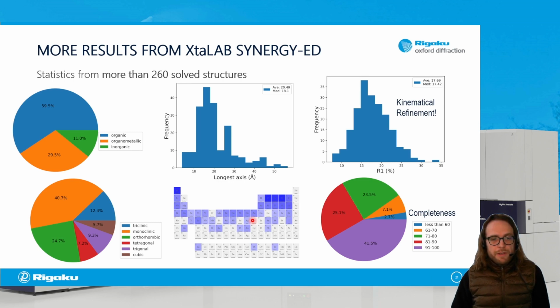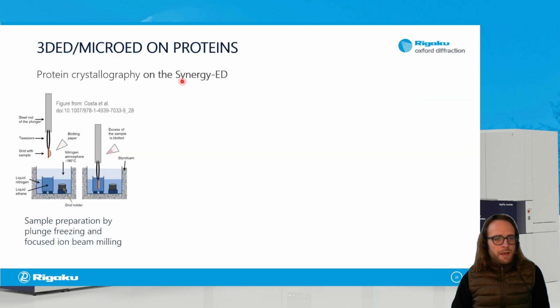Another thing I would like to highlight, which is actually not even included here, is that we can also conduct 3D electron diffraction on proteins. The way you do this is that you prepare protein crystals on a 3 millimeter sample grid in the same way as you would do in cryo-electron microscopy. So you apply a few microliters of crystal slurry on such a grid. You quickly plunge freeze this into a container of liquid ethane, which will turn the water into vitrified amorphous ice.